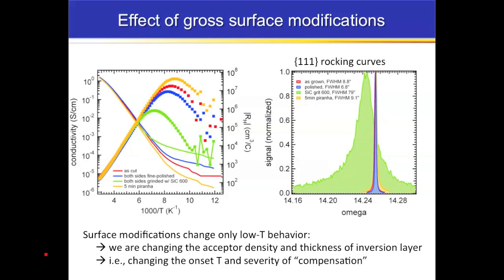If there is such a surface inversion layer in pyrite, we should expect to be able to change it by manipulating the surface, either passivating surface states or creating more acceptors. So I show here what we call gross surface modifications, where we've taken an as-cut sample in the red, and we fine polish both sides and get this blue data. We then grind both sides of the material with rough silicon carbide paper to intentionally damage it, and we get this green data. Then we do a piranha etch, which removes all the surface damage, and we actually get improvement in the overall performance of the material, in the orange data.